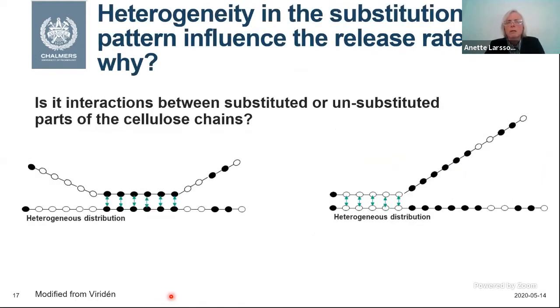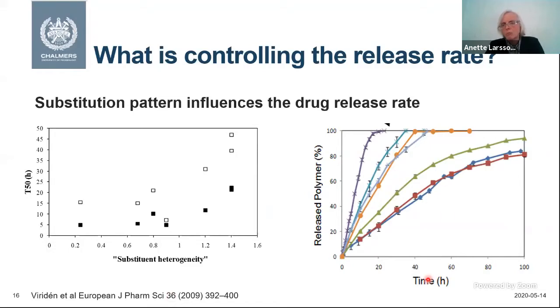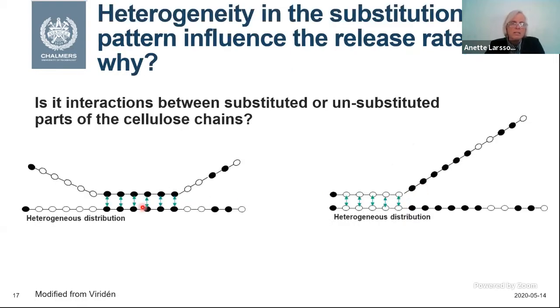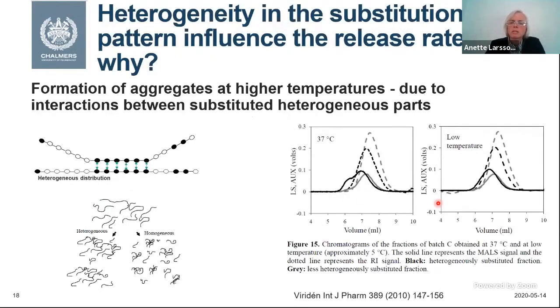But then comes the question: okay, so it depends, a slower release is gained when you have more heterogeneous materials, but why? Why does this happen? Is it due to interactions between the substituted patterns, or is it due to interactions between unsubstituted ones? And to check that, we did SEC measurements. This is size exclusion chromatography, where we have the RI detector and a multi-angle laser light scattering detector, giving an indication of the size of the things that enter the detector.